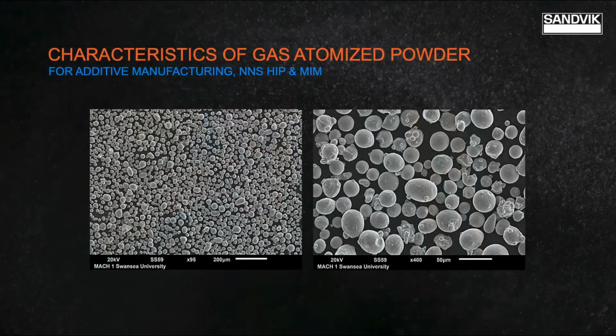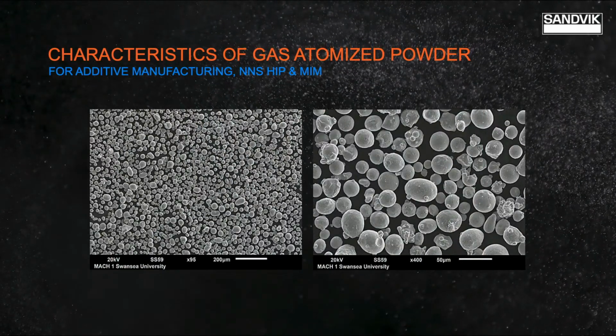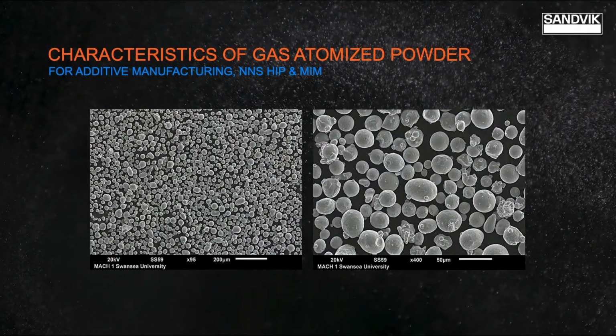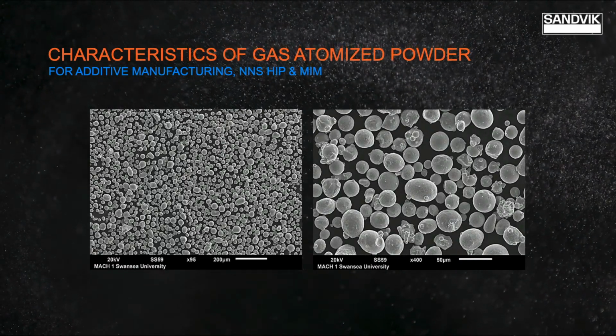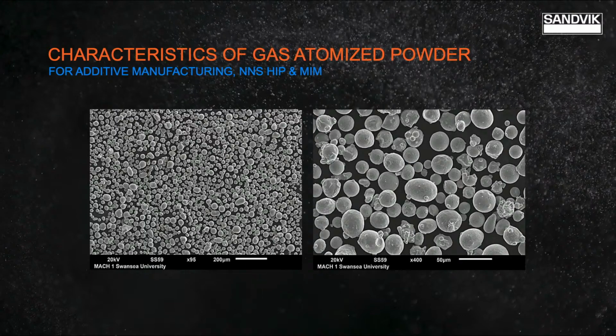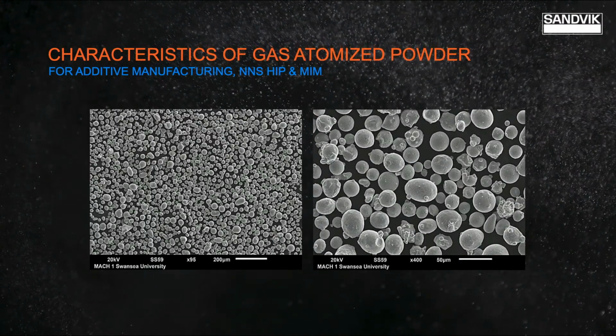Well, characterization of the powders is very important, from the shape of the powders, where we can see examples on the micrographs, and the spherical shape typically produced by the gas atomized powder process. So they're spherical but not perfect, but they also involve a melting process, which is inherently clean, melted under inert gas, typically with low oxygen levels and low levels of impurities. High tap density, so you can pack the powder in the powder bed, and with refined microstructures, and this leads to enhanced properties in the product.